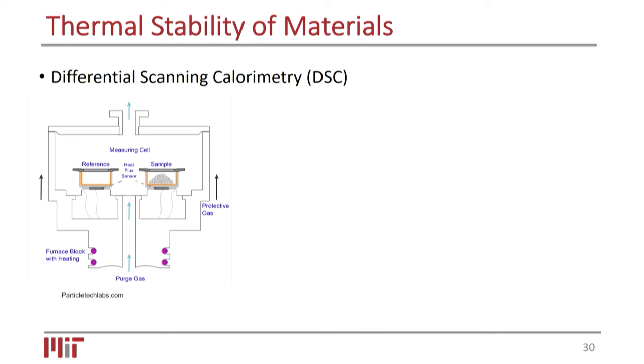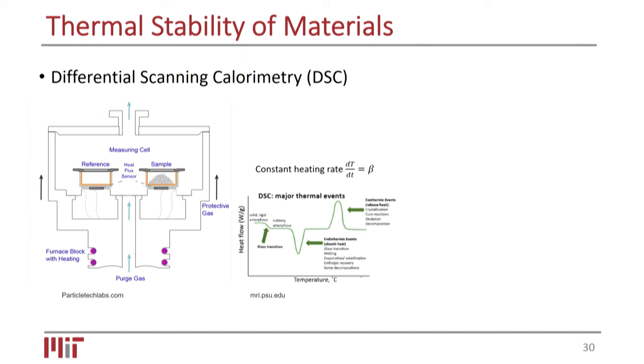And this is called differential scanning calorimetry. So essentially, we would take apart the battery and separate the materials and put them in these crucibles and run experiments like this. By controlling the temperature history, by having a constant heating rate, we can track the heat flux inside the system, compare the sample that we want to test with a reference. And the data would look something like this.